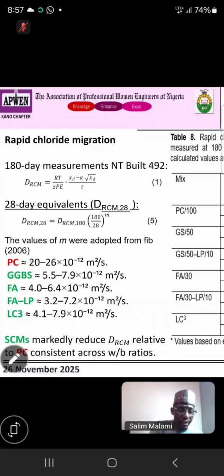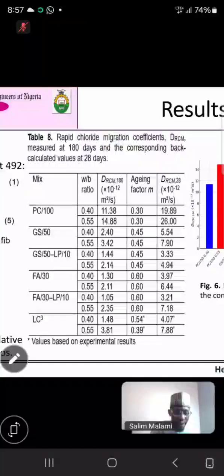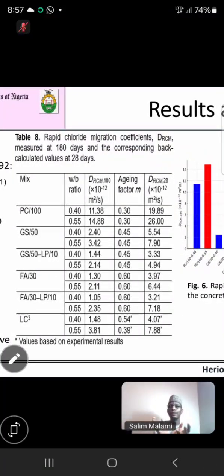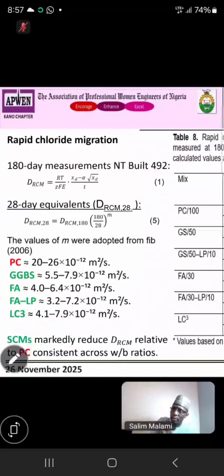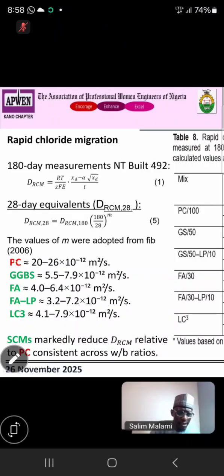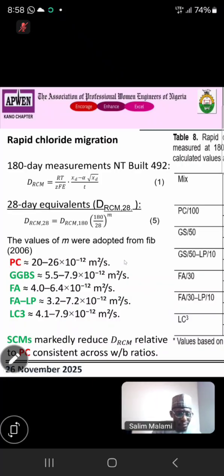So the result of this: PC has 20 to 26 chloride diffusion coefficient. It has higher. We need a small value, because it's the measurement of how chloride can penetrate into the concrete. So the higher the penetration, the higher the effect. So we need less penetration, less chloride diffusion coefficient. If you see from our result, PC has 20 to 26 meters square per second. GGBS has 5.5 to 7.9. FA has 4 to 6. FALP has 3.2 to 7.2. LC3 has 4.1 to 7.9. This means PC has the highest value. So this means low carbon concrete has less penetrability of chloride.